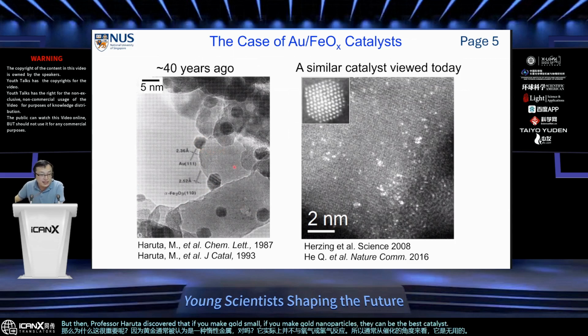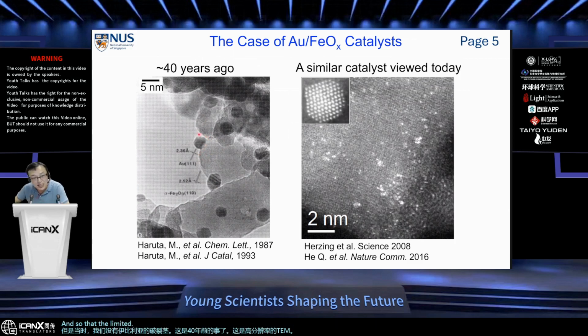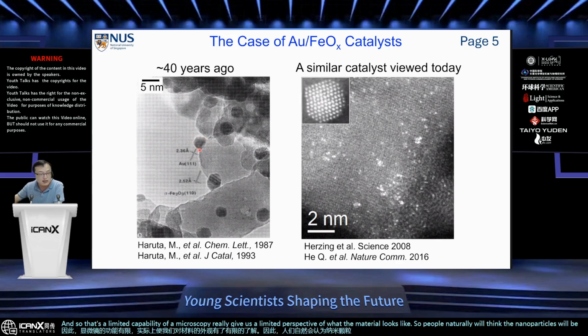But at the time, we didn't have an aberration-corrected STEM. This was 40 years ago. This is a high-resolution TEM. It's the best we had got. And so the limited capability of microscopy really gave us a limited perspective of what the material looks like. So people naturally thought nanoparticles were responsible for all the catalytic performance, and that led to further theory and a lot of experiments.